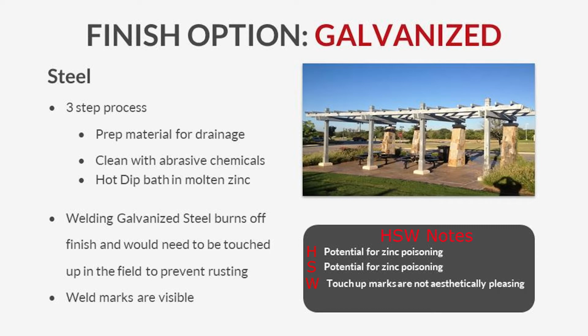After the steel is cleaned, it's pickled in a solution of hydrochloric or sulfuric acid to remove oxides and mill scale and re-rinsed. The next step is fluxing. The steel is dipped in the flux to clean off the oxidation that has developed since the pickling and to protect against further oxidation before entering the galvanizing kettle. Next, the steel is finally ready to be dipped into a molten zinc bath of around 830 degrees Fahrenheit. The steel remains in the bath until the steel itself reaches the bath temp.